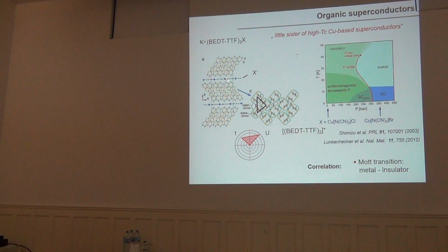And if you see the structure of these systems, it looks horrible, but it's not. Basically, the structure of these systems is based on these BEDT-TTF molecules. They form pairs, and if I just cut now perpendicular to the plane, these pairs are arranged in a triangular lattice. So basically I have a triangular lattice of dimers of molecules, and these molecules are separated by anions, and the chemistry of this system is that these anions basically suck an electron, one per dimer, so that at the end of the day what I have is a triangular lattice with one hole per site, or one particle per site. So it is the same as in the high TC cuprates. In the high TC cuprates I have a square lattice, here I have a triangular lattice.